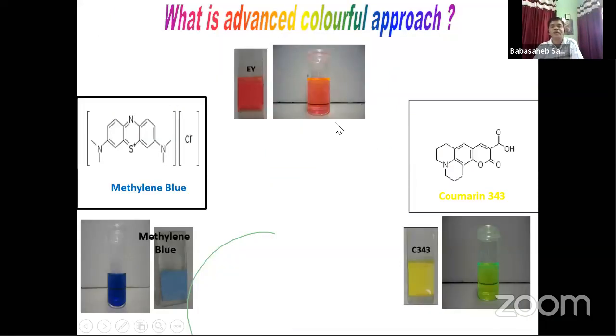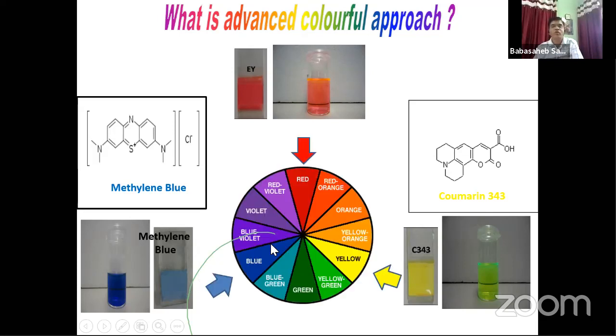So we made a more advanced colorful approach, in which we have three dyes in our hand: eosin Y with the red, the yellow coumarin 343, and methylene blue with the blue color. So we can have red, yellow, and blue. If you mix red with yellow, you can get orange. If you mix yellow and blue, you can get green. If you mix red and blue, you can get violet. By just mixing the different dyes, it is possible to generate different colors and different types of solar cell. So we tried red and yellow to get the orange color, just by chemical mixing of these two dyes.